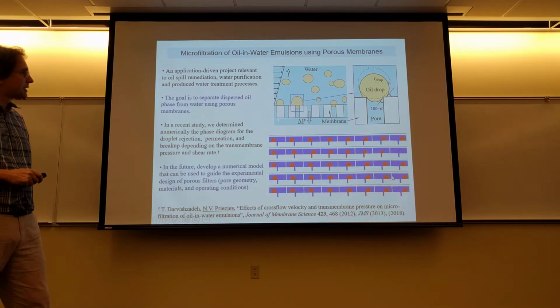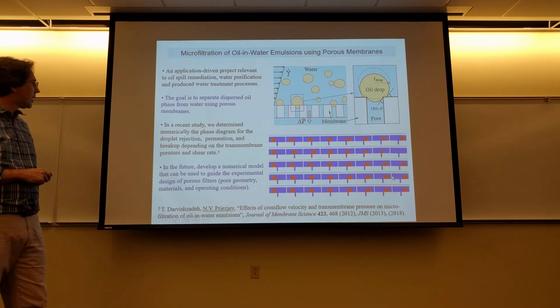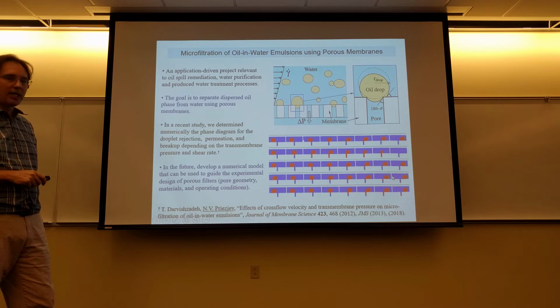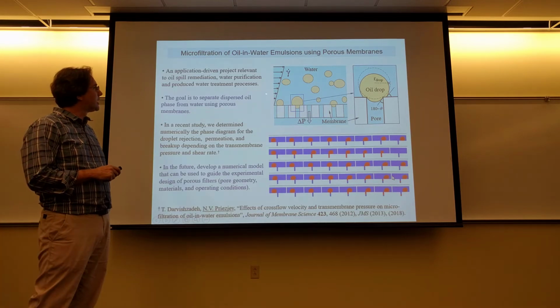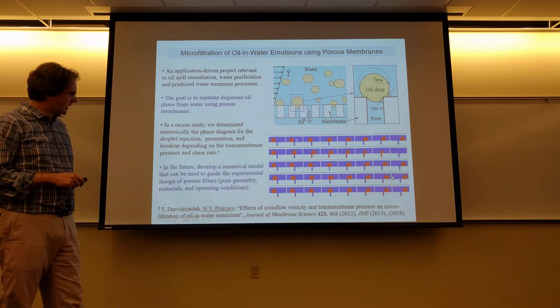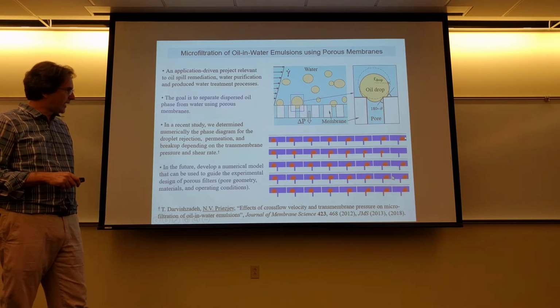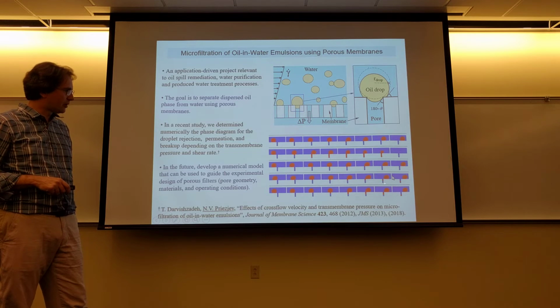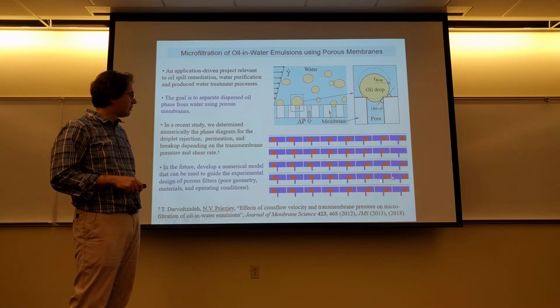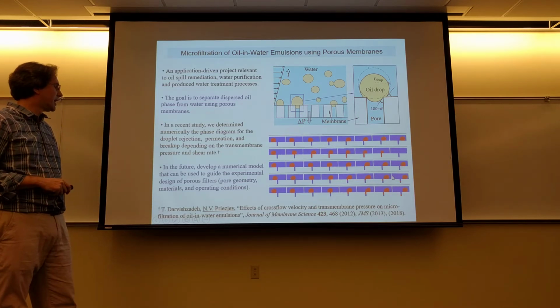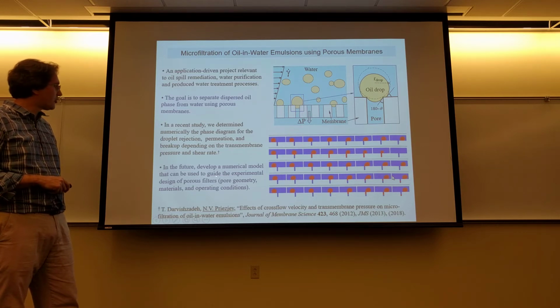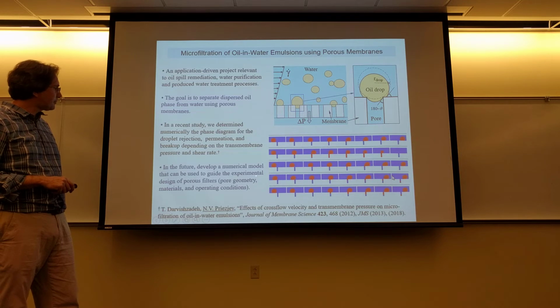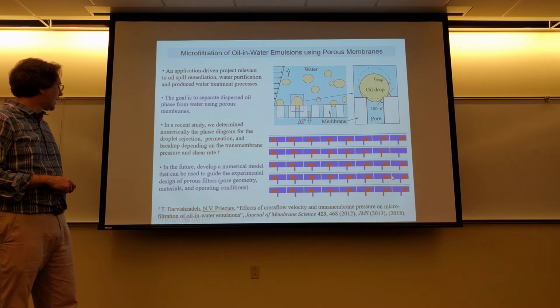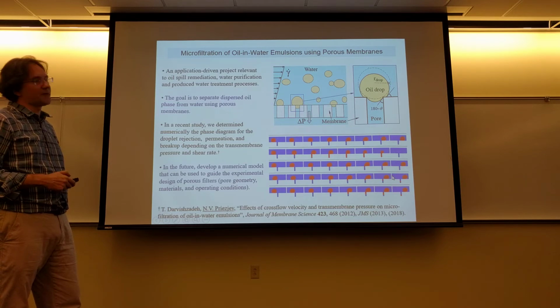We considered various physical parameters and came up with a numerical phase diagram where, depending on the transmembrane pressure and cross-flow shear rate, we can observe a rejection of the oil phase, then penetration of the oil droplets, and a more subtle situation is when droplets break up at the entrance of the pore and the membrane will be leaking. More information can be found in the papers, and this research in general is relevant to experimental design and development of novel porous filters.